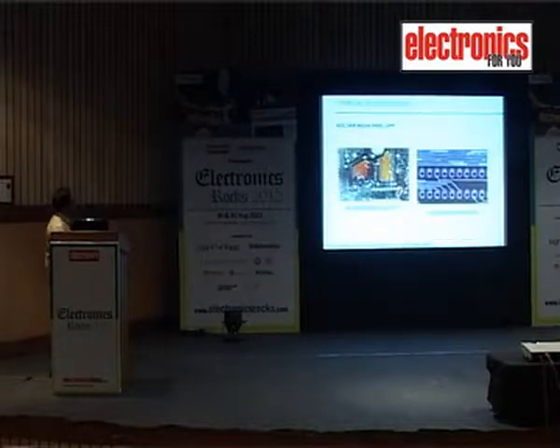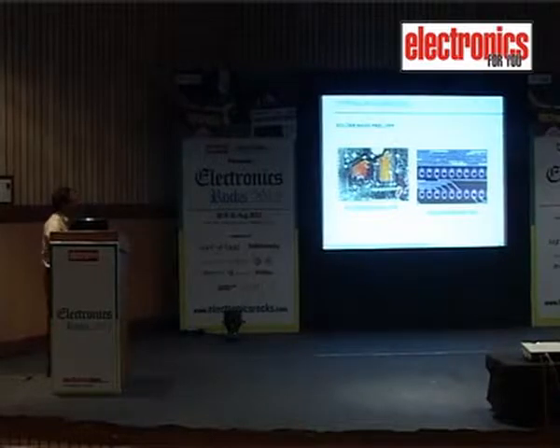And if you see the solder mask material getting peeled off, and as you know, space environment has a very hard vacuum which will go up to 10 to the power of minus 12 torr. When we subject these type of PCBs under those vacuum conditions, it can make the solder mask material peel off or degas, and it can affect the whole performance of the spacecraft. So if such phenomena is seen, the boards are rejected and the material is subjected for qualification.